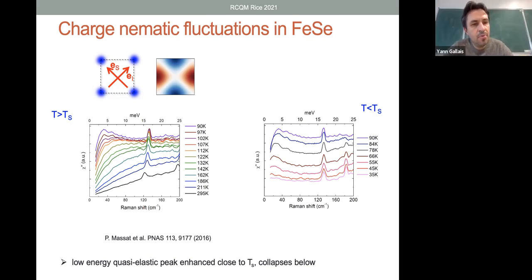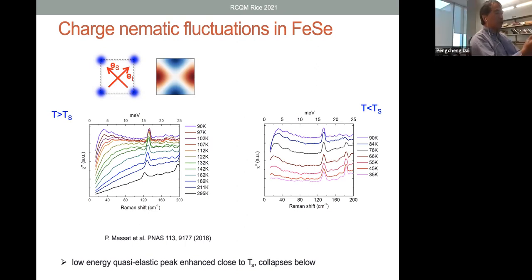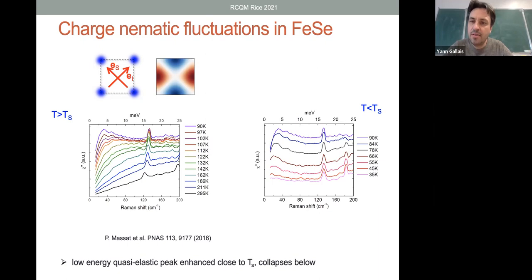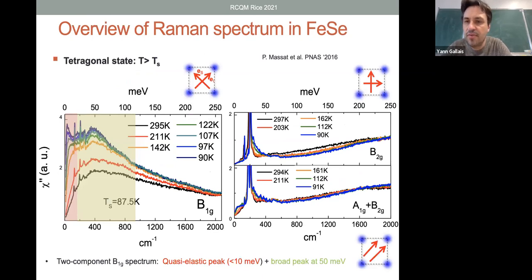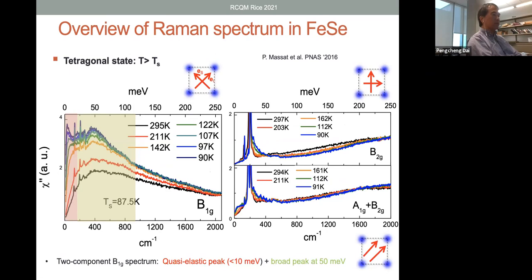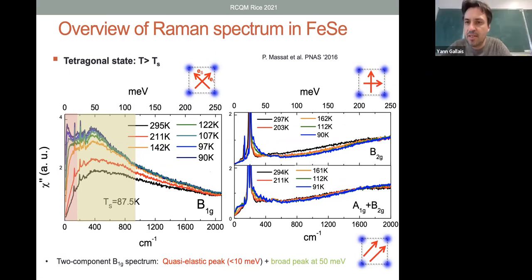The polarization that we use naturally differentiates between them. If you want, we are x squared minus y squared naturally. So I was just curious, if you include the larger energy range, you still see similar behavior? The low and the high energy, you mean? Yeah. The high energy is critical. If I decide to integrate up to, let's say, 250 milli-electronvolts, the full range, and do a Curie-Weiss-like analysis, it would further decrease my T node. It would be less critical. So the full nematic spectrum would be less critical. If I concentrate on the most critical part, the low energy one, then I get a slightly higher T node. That's the one I described before.